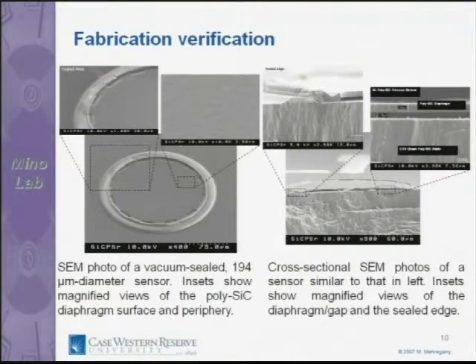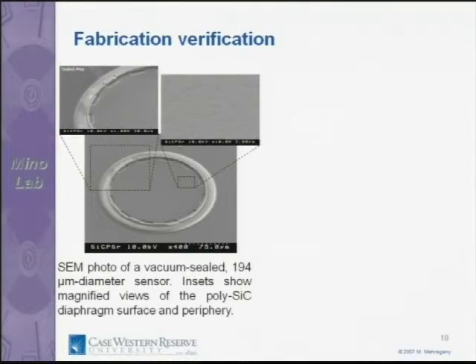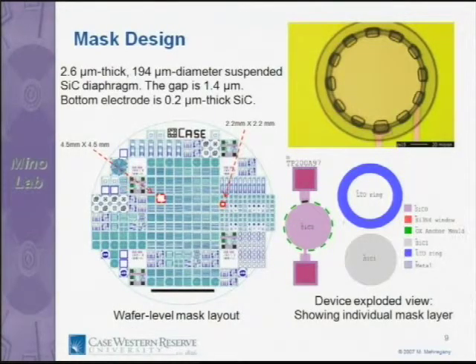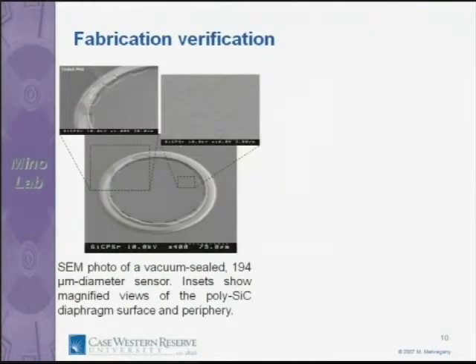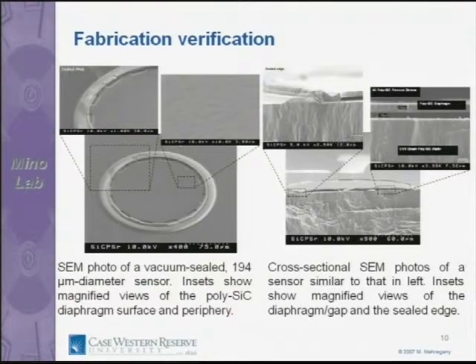In cross-section, you're seeing the silicon carbide wafer, the silicon carbide diaphragm, and the gap between the diaphragm and the bottom electrode forming the parallel plate capacitor. Here's a magnified view. The diaphragm is about 2 microns thick. This gap is about 1.5 microns thick, and the substrate. So you get a pretty good view of what this mask set and what this picture comes out to be after fabricated, okay?